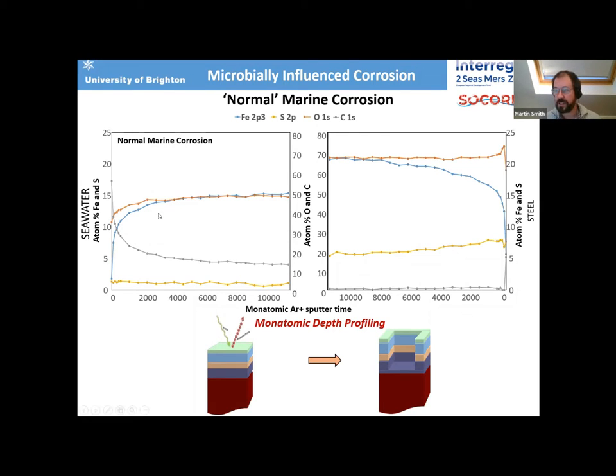So what we've done in this case is take a sample, split it in half, inverted one half, and we've depth profiled from the outer surface inwards and from the inner surface outwards, which is why the scales are inverted on these two plots. But what you can see, we go from a few atomic percent sulfur in the outer part of the material up to around 10 atomic percent sulfur at the steel surface. So the yellow line here is the sulfur concentration going into that corrosion sample. This was supposedly normal marine corrosion, and we've still got sulfur contents here.